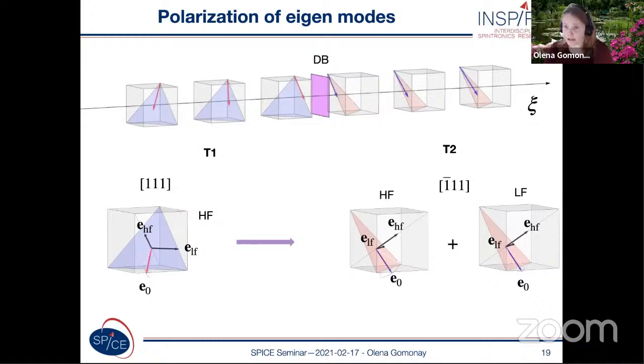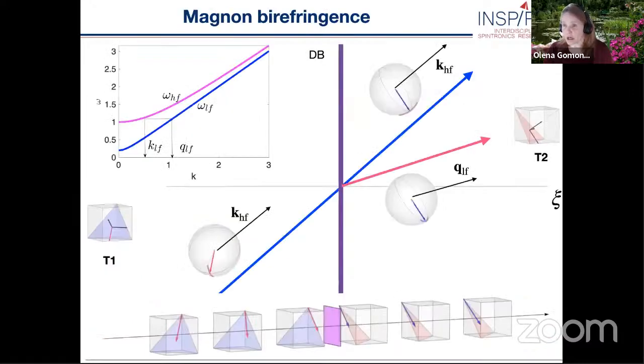And this effect is very similar to the effect of optical birefringence, when the optical ray goes through the sample and then splits into 2 rays with different polarizations, different wave vectors, and the same energy. So we can say that magnetoelasticity is responsible for a possible magnon birefringence effect in the case of T-domains in nickel oxide.